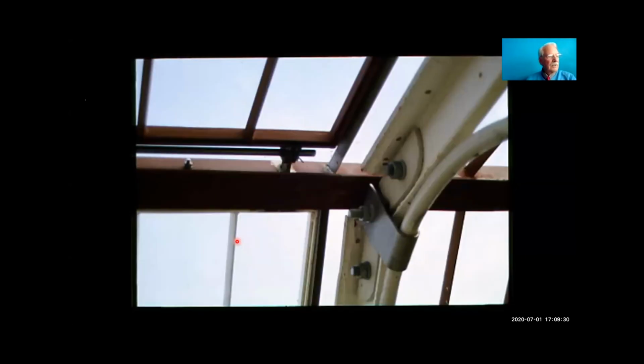Now, just finally, as we're getting towards the end of our time, I want to show you where the roof was repaired here. This, again, is the Water Lily house in Kew Gardens that I just showed, but the roof glazing bars, in many cases, were too far gone, too far rusted to use. So the specification at the time was to use stainless steel. Now, there is a problem with stainless steel. It has a lot of nickel in it, and nickel is aggressive to iron, to wrought iron and cast iron and steel. And if you put them together in a wet environment, like a plant house, then the stainless steel, whether it be in glazing bars or in bolts, will attack the iron.